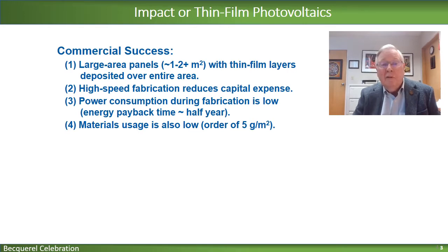So thin film photovoltaics have had both a commercial success and also at the cell level have been achieving pretty high efficiencies. In the commercial world, we're talking about large area panels, very much like the silicon ones, ranging from about a square meter up to over 2 square meters in area. And they're all made by depositing thin film layers over the entire area of the panel. This allows fairly high-speed fabrication, and it reduces the capital expense involved. The power consumption during this fabrication is relatively low. The energy payback time is roughly half a year. And at the same time, the materials usage, as you might imagine for thin films, is pretty low.